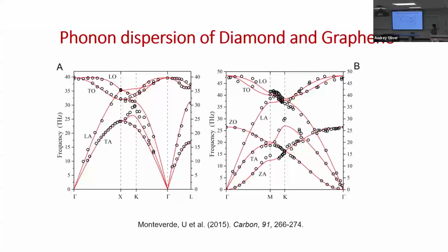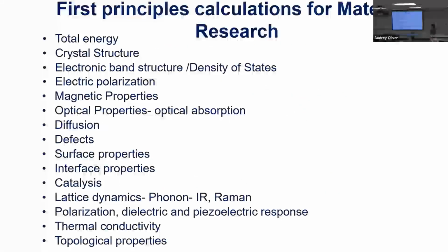Okay, so based on the symmetry of the crystal, we can also resolve those frequencies to IR active or Raman active. Okay, so what we can do using DFT, we can calculate total energy of the system. Right? We can predict crystal structure, calculate electronic band structure and density of states. And we can extract a lot of information from band structure as well, right?